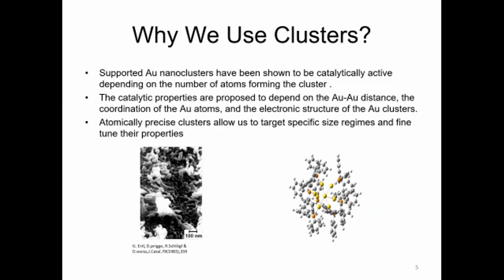To have this cluster as stable as we can, we have to protect it with ligands. These ligands around the cluster are for stabilizing the gold core. But once we need to do the catalytic reaction, we need to remove the ligands so the gold core is naked and can take part in the catalytic reaction.